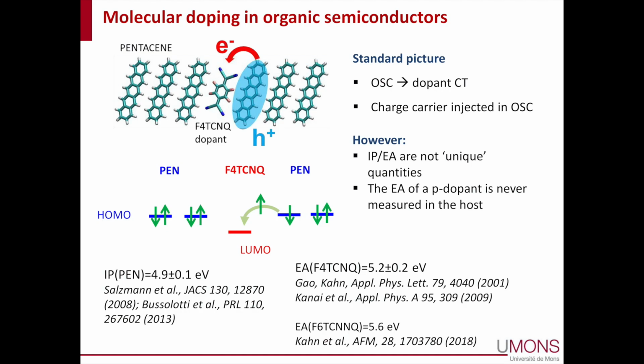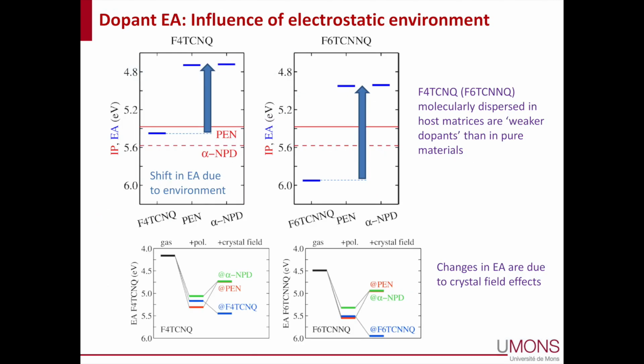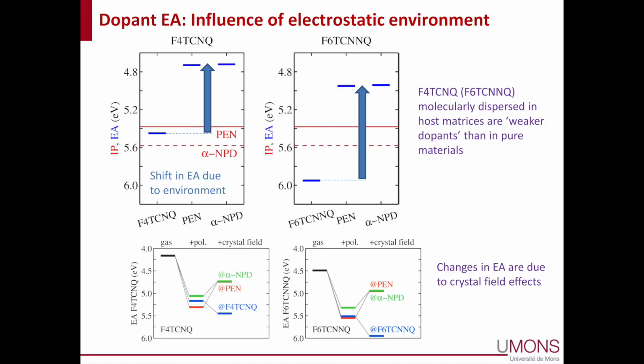Well, this simple cartoon has to be considered with caution, because in reality, the LUMO level of the dopant turns out to be very different if you look at the energy level of the dopant in its own environment. So if you measure the electron affinity of the F4TCNQ, for instance, in a pure F4TCNQ film, or if you measure it in the host material, typically this energy level, in the case of F4TCNQ or F6TCNNQ, shifts up.